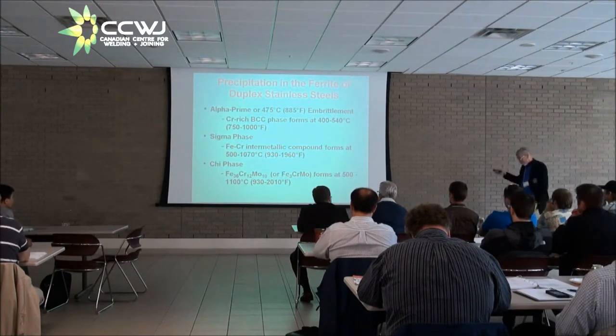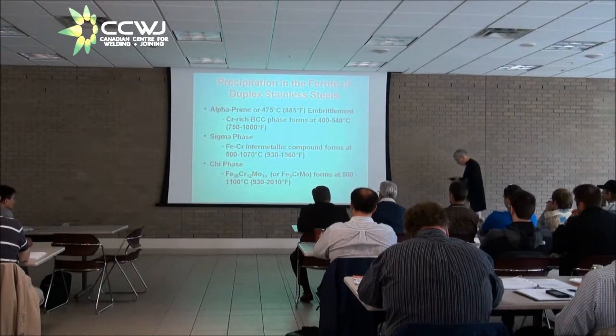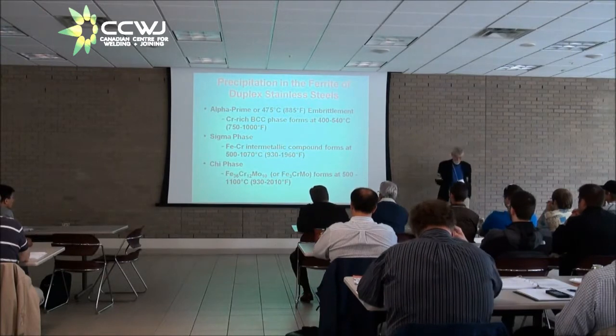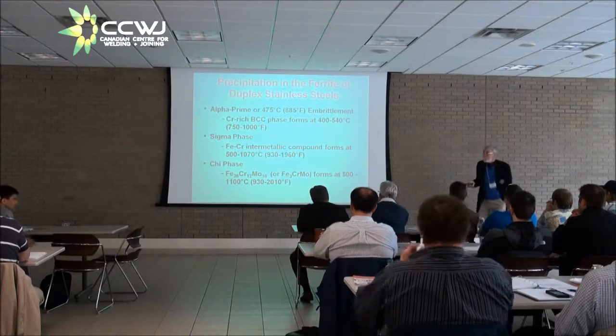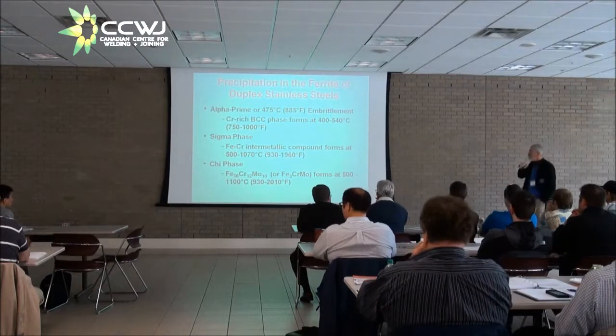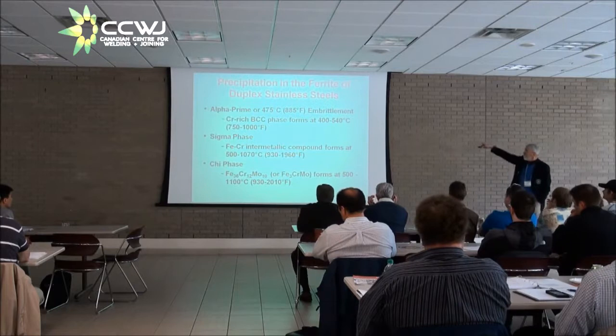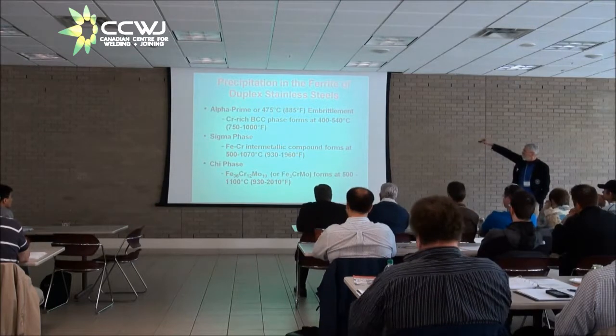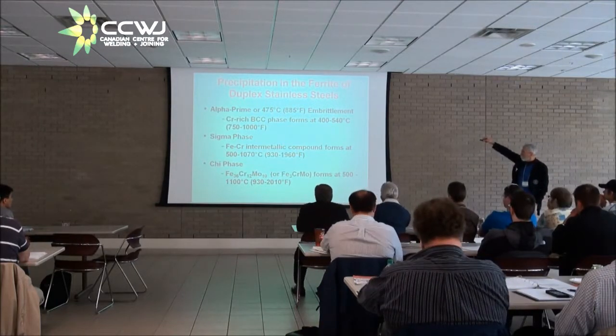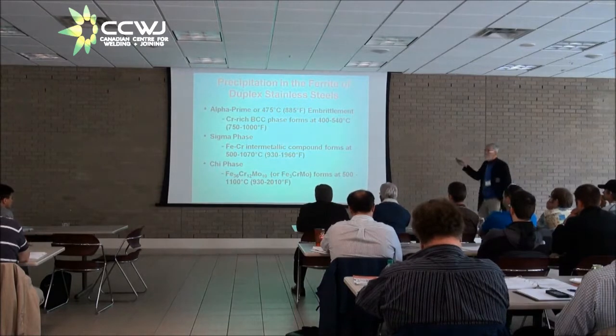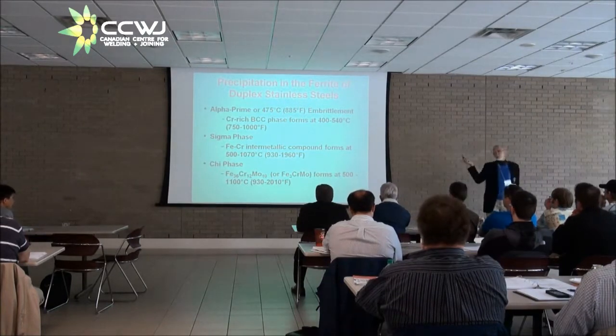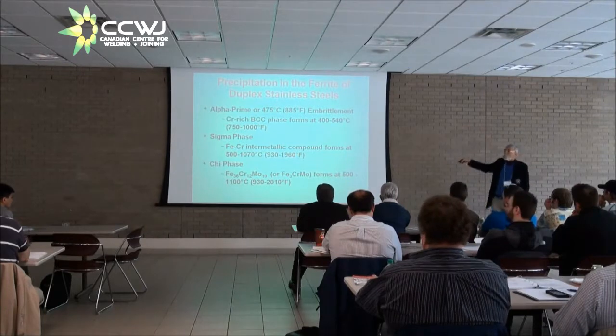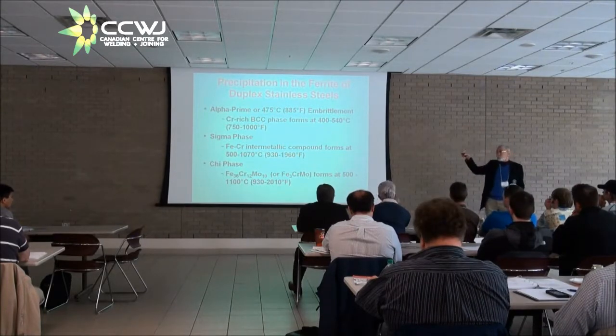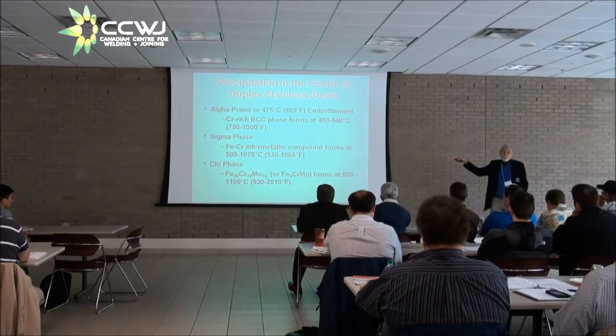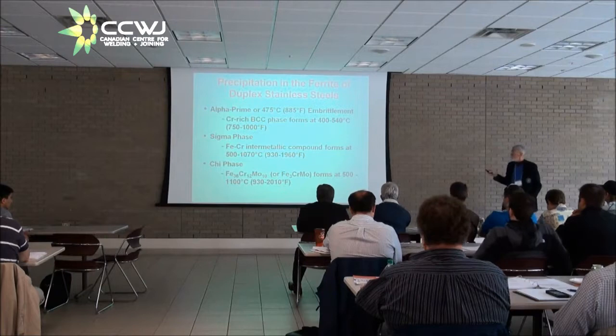Well, that alloy doesn't have any useful properties above 1100 degrees C. It's sort of like peanut butter in terms of mechanical properties. So the real interest is in below 400 C. Now here you will see this is the temperature range where the alpha prime phase will form in a few hundred hours. If you go to 10,000 hours, that temperature comes down. And so people will say 300 degrees C is the maximum service temperature for these alloys, or maybe even 250. So those are all limitations.